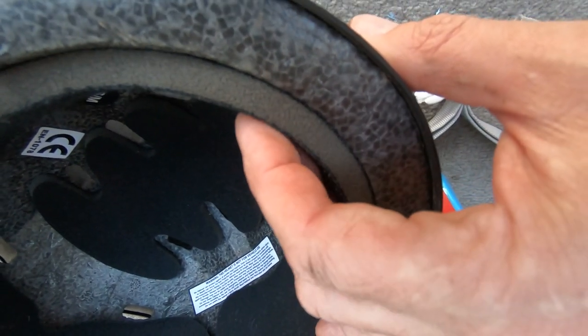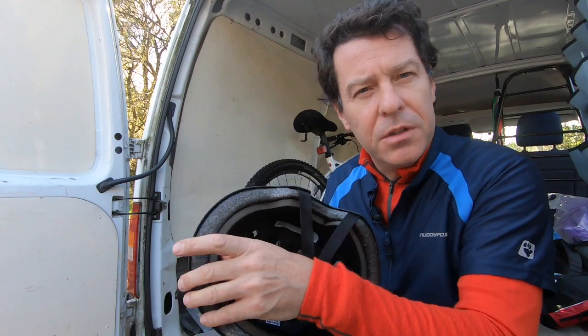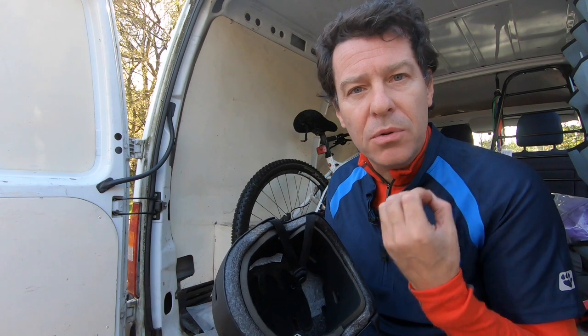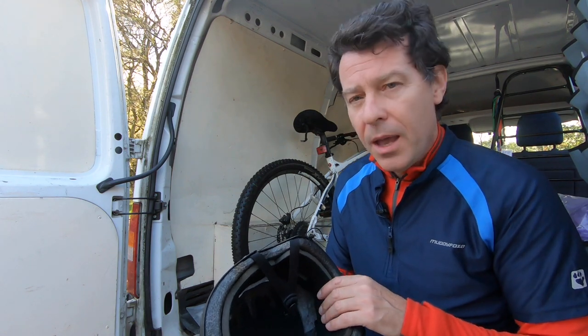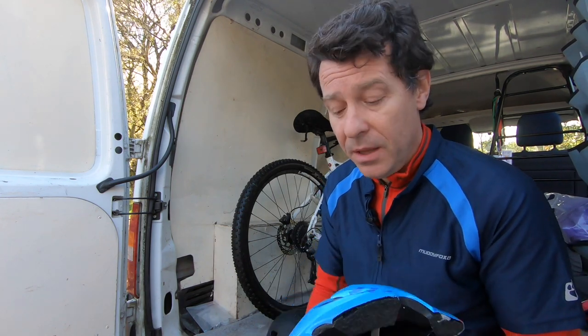The liner is about an inch thick and it's made of two layers. Firstly, a soft, bouncy material that just takes the knocks and bumps. The thicker material is often the more protective one. In an impact, this permanently deforms — it absorbs all of the impact that normally would be taken by your brain. However, once that foam has become deformed, it won't squash nicely next time it has an impact. It leaves a gap and that ceases to protect you. This is why you shouldn't buy a second-hand helmet. Even if it looks good on the outside, you don't know whether that polystyrene inside has been compressed, particularly with the cheaper materials like polystyrene.